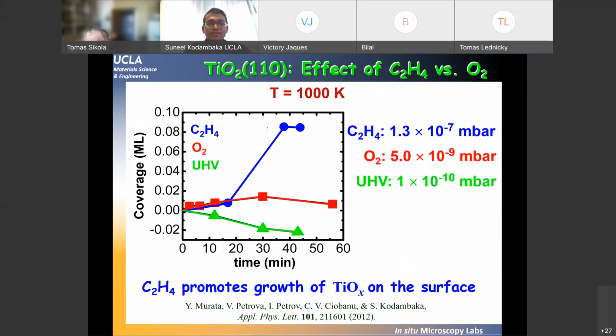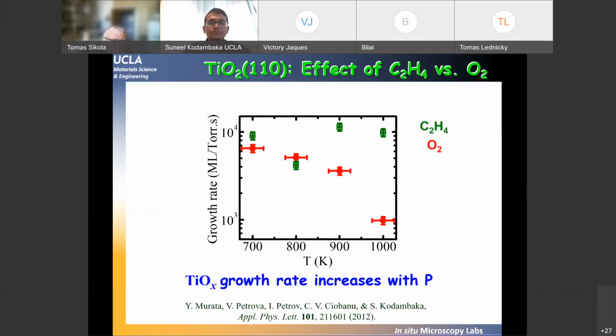Okay, and so this was puzzling for us for a minute, or well, for a lot of experiments. And then we did a series of experiments as a function of ambient and as a function of temperature and time. And what we observe is that a mixture of ethylene and oxygen with small traces of oxygen significantly enhances the growth of the stripe phase rather than just annealing in pure oxygen at a given temperature. And annealing, of course, in vacuum, you lose the oxygen from the surface, and so the stripe phase decreases if you are annealing in vacuum.